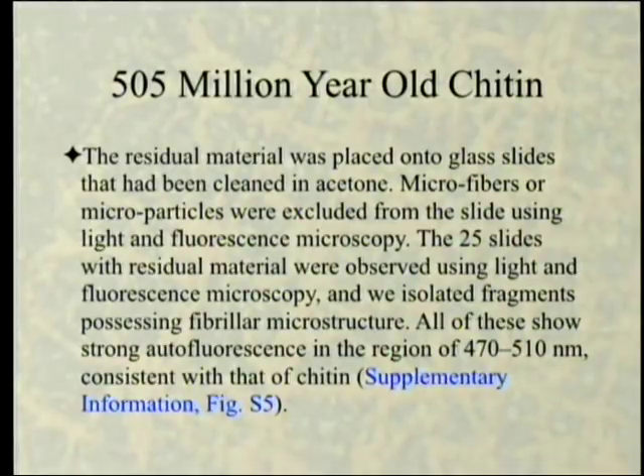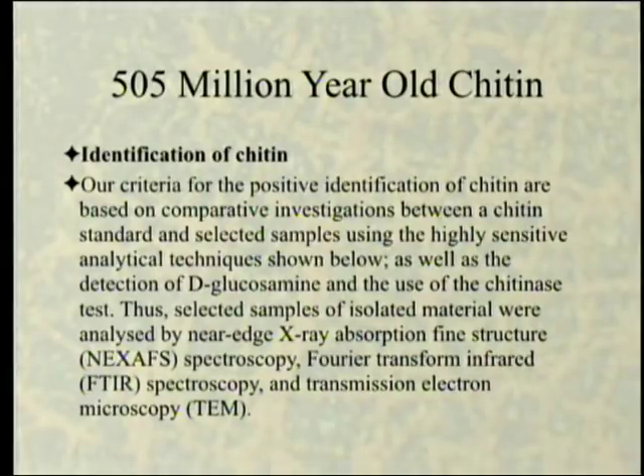The 25 slides with the residual material were observed using light and fluorescent microscopy, and we isolated fragments possessing fibrillar microstructure. All of these showed strong autofluorescence in the region 470 to 510 nanometers, consistent with that of chitin. That's basically shining kind of a near ultraviolet or violet light on them, and they fluoresce. Identification: how do you know it's really chitin instead of something that just looks like chitin? Our criteria for the positive identification of chitin are based on comparative investigations between a chitin standard and selected samples using the highly sensitive analytical techniques shown below, as well as the detection of D-glucosamine and the use of the chitinase test. Thus, selected samples of isolated material were analyzed by near-edge X-ray absorption fine structure spectroscopy, Fourier transform infrared spectroscopy, and transmission electron microscopy.